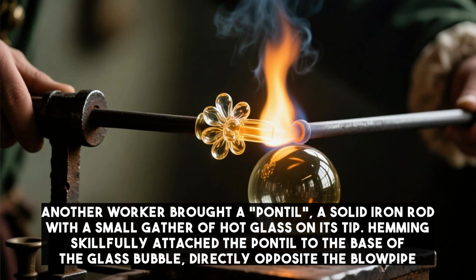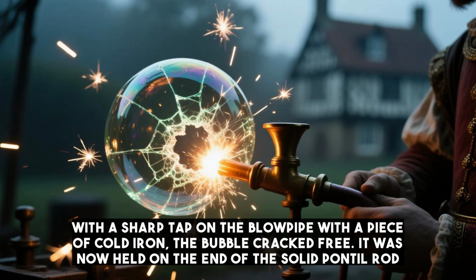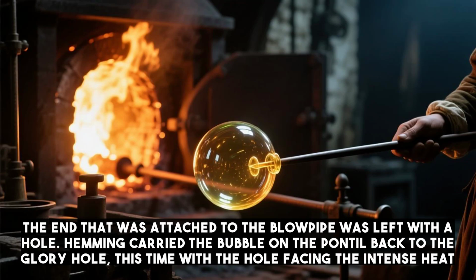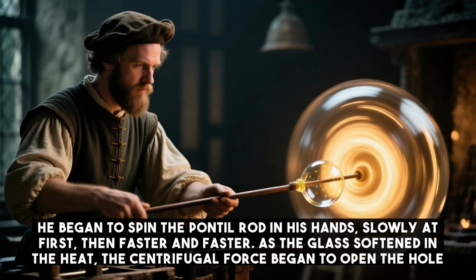Another worker brought a pontil, a solid iron rod with a small gather of hot glass on its tip. Hemming skillfully attached the pontil to the base of the glass bubble, directly opposite the blowpipe. With a sharp tap on the blowpipe with a piece of cold iron, the bubble cracked free. It was now held on the end of the solid pontil rod. The end that was attached to the blowpipe was left with a hole. Hemming carried the bubble on the pontil back to the glory hole, this time with the hole facing the intense heat. He began to spin the pontil rod in his hand, slowly at first, then faster and faster.